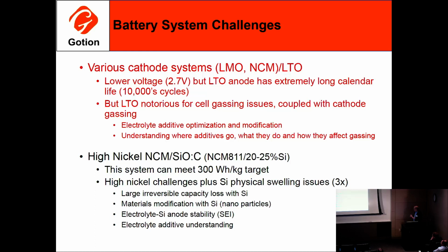The next system that we're working on is LTO. LTO anode is great. You can go tens of thousands of cycles with this. So this is perfect for applications where we really want long cycle life. You couple that with either LMO, but typically we're looking at NCM type materials. But again, you add another complication. LTO is notoriously known for gassing, specifically on formation and even a little bit over long cycle life.